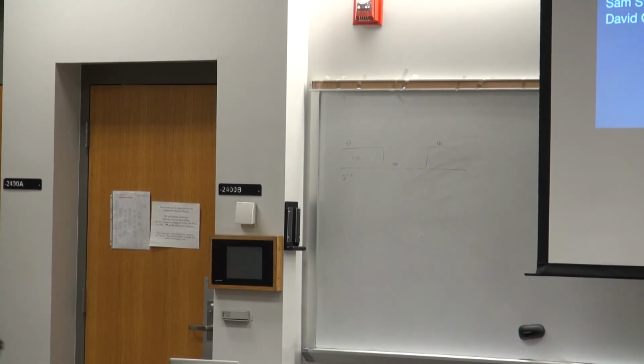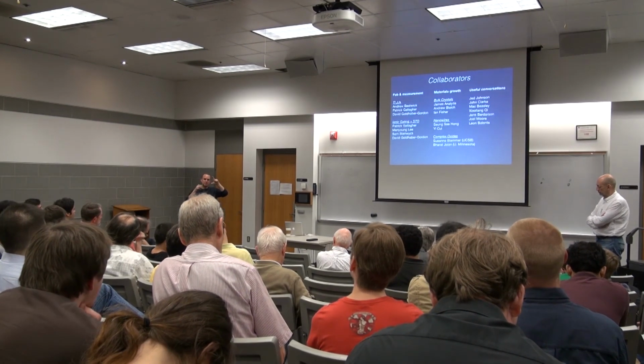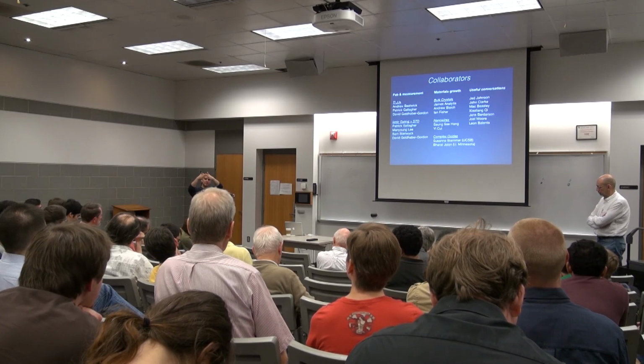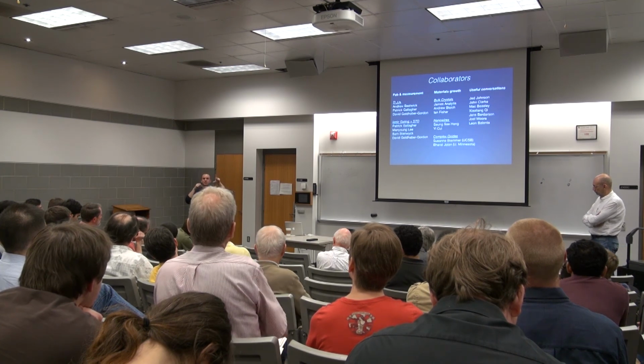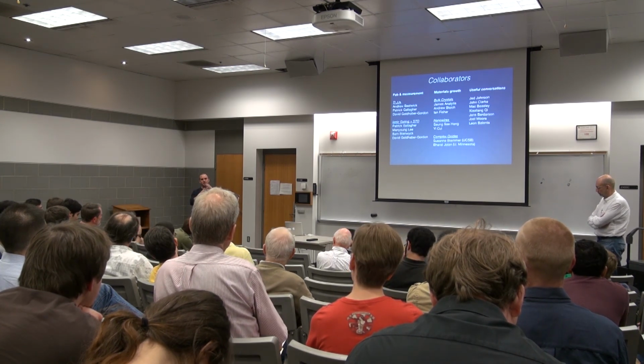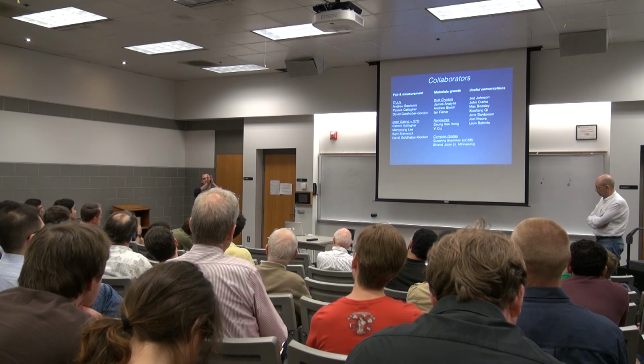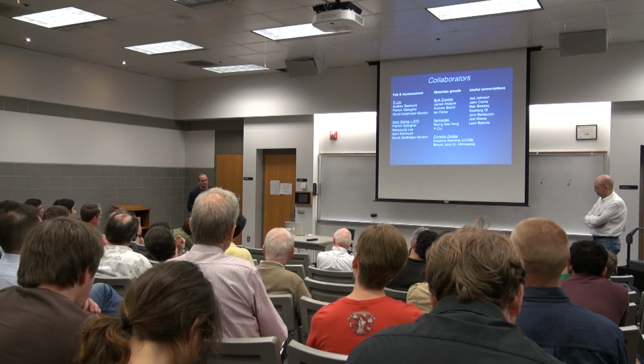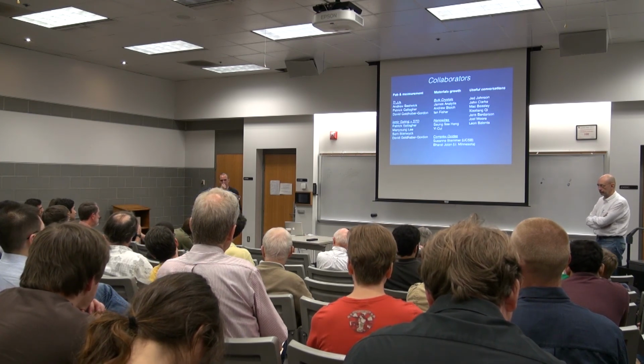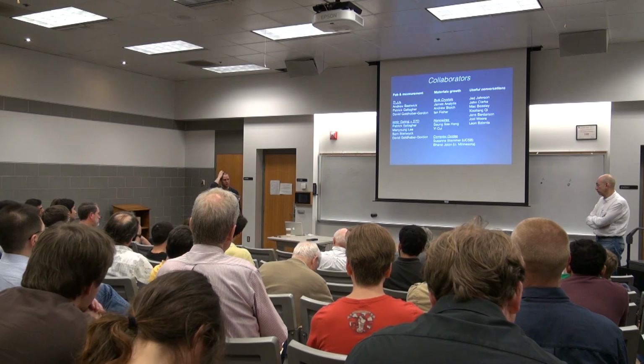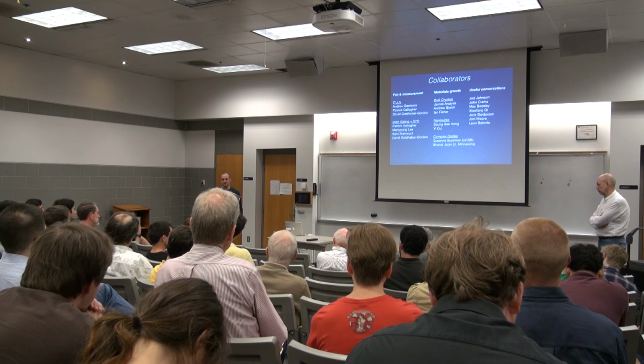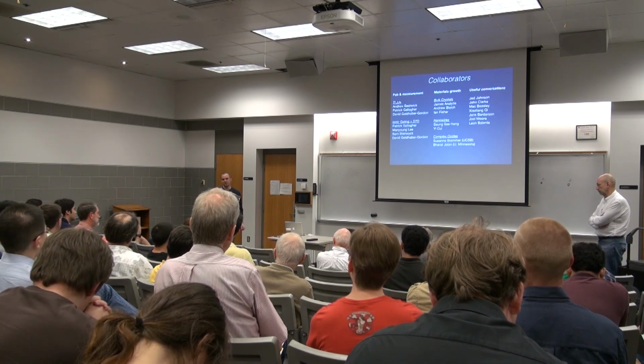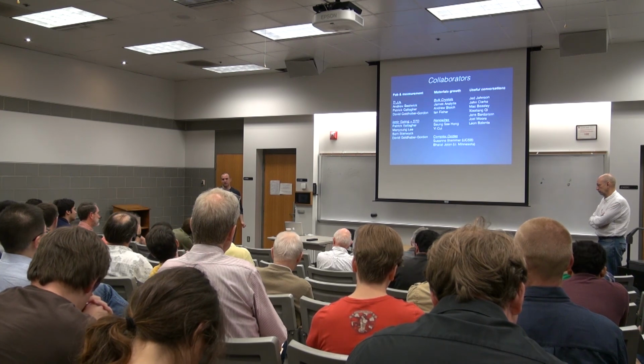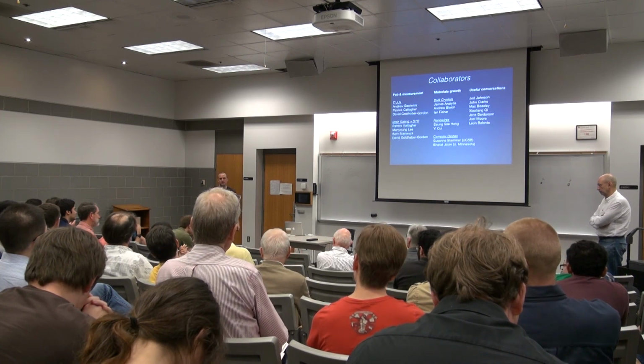I guess the only very obvious difference between the two is that as you open up the gap at k equals 0, you should see a collapse of the Majorana state to 0, and then as you further apply the magnetic field, the gap should open back up and close again. So you should see a peak at 0 that opens back up again and then closes, and you can see that behavior a little bit better in the Weizmann work. And there's been a whole collection of work from a former student of Leo where they see a similar thing but ascribe it to the unusual nature of the Andreev bound states in the system, not Majorana physics.